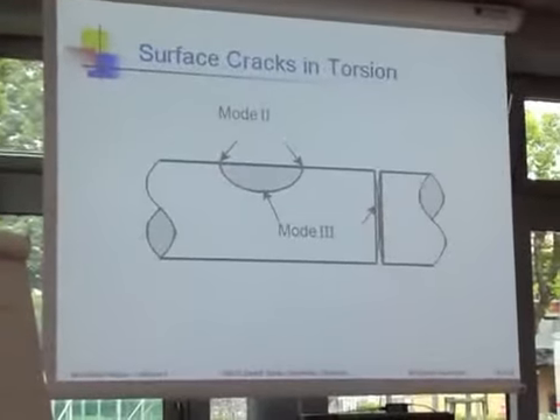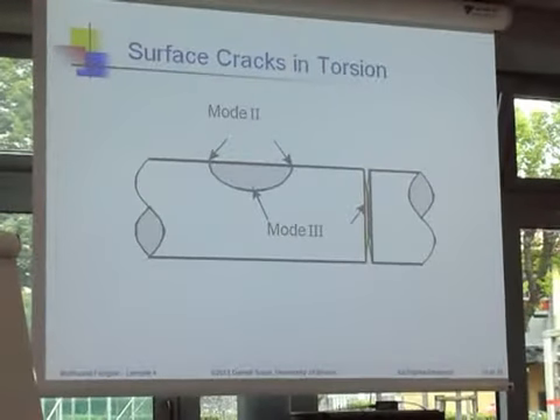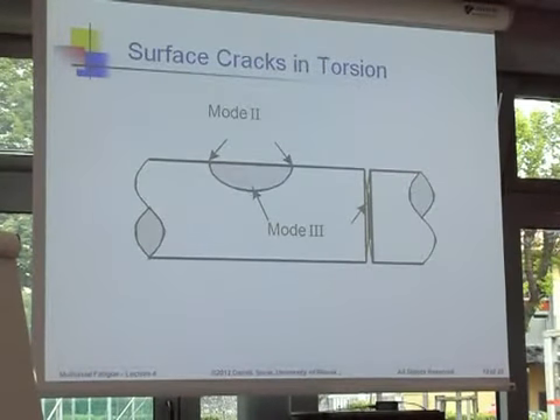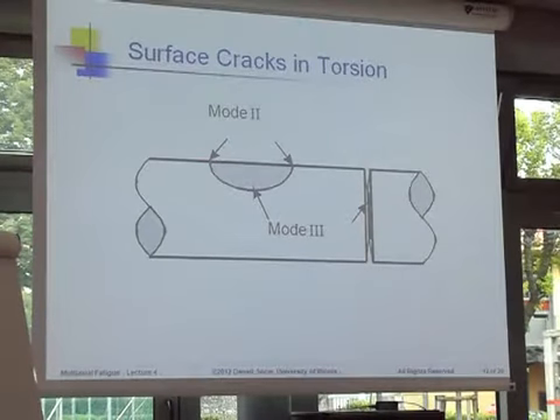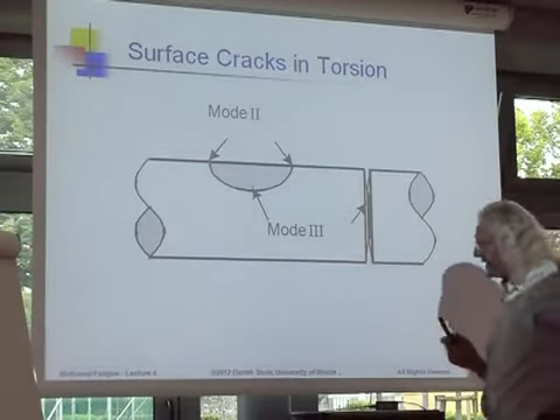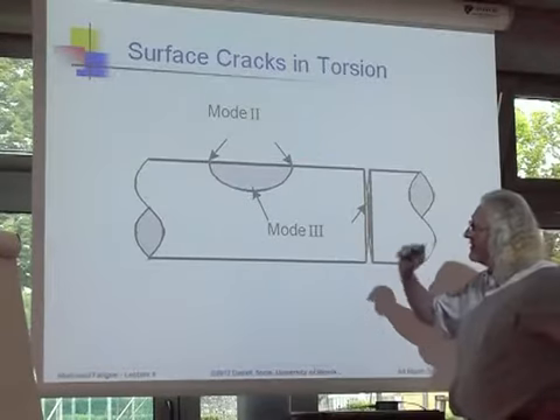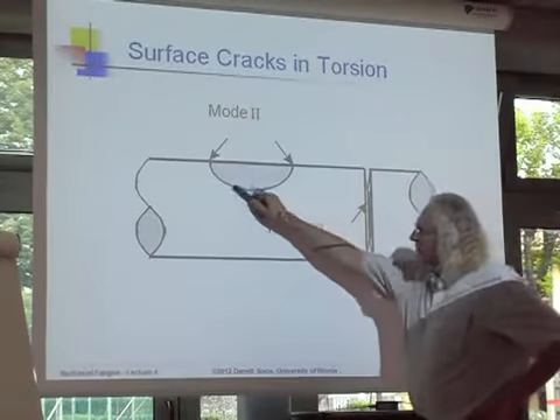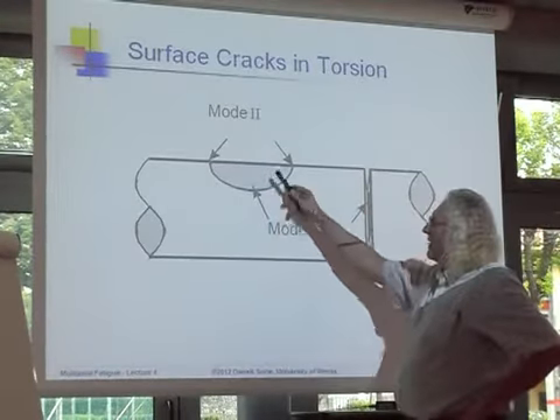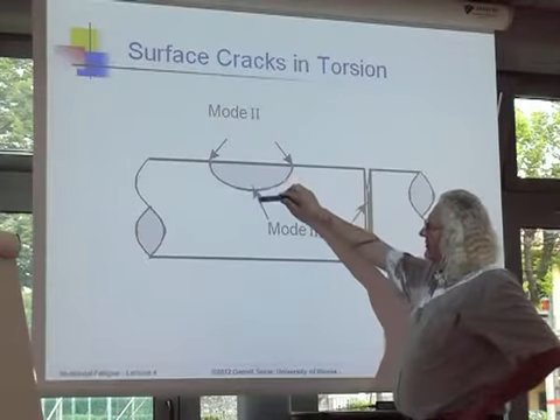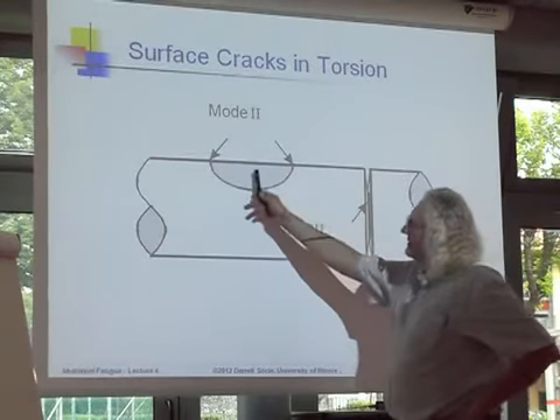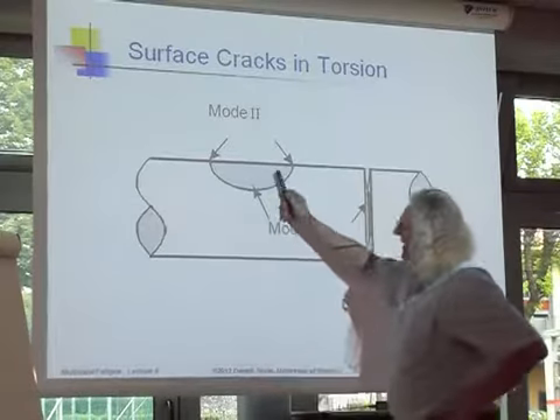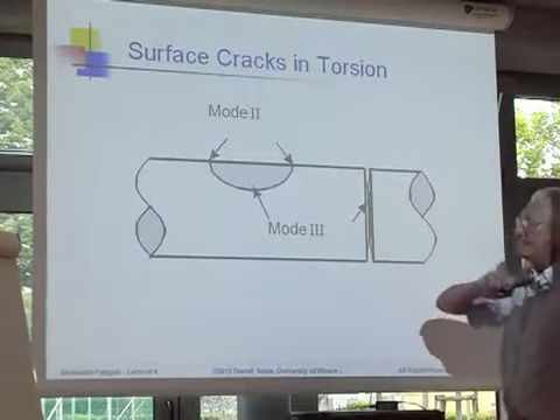So let's look at some of these others. And that is, of course, in torsion, you get two different types of cracking. And if you have a bar in torsion, you can have a crack which goes in on the surface like this. Of course, because in a bar in torsion there's always a stress gradient, this crack tends to grow along its length more so than into the depth.